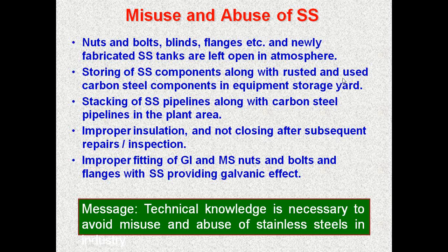Storing stainless steel components along with rusted and used carbon steel in an equipment storage yard is very commonly seen in any industry. You should not do that. You have to separate them. Stacking stainless steel pipelines along with carbon steel is also a very dangerous practice. Improper insulation and not closing after subsequent repairs and inspection is also very important. If you have an insulated component used for high temperature or any other application, whenever you do some repair or inspection, you should close it properly so that the place is not vulnerable to chloride or any other aggressive ion entering and starting localized corrosion.